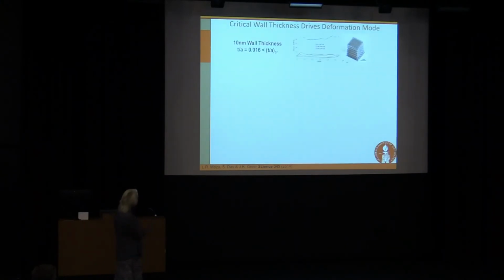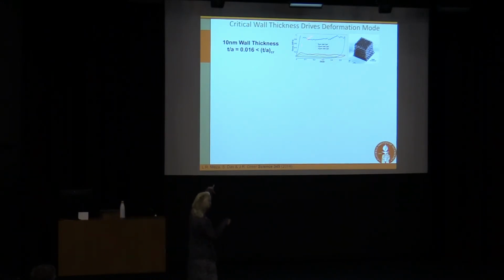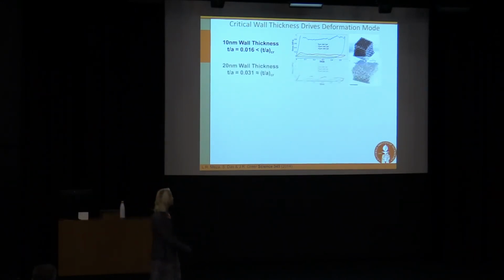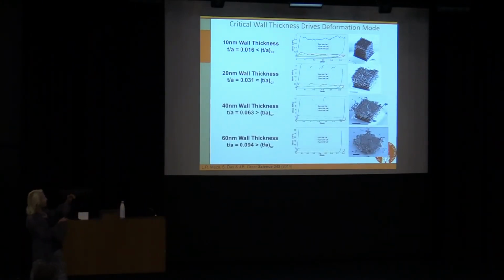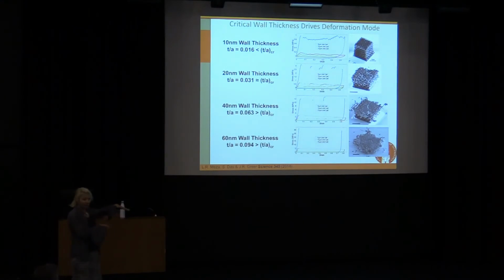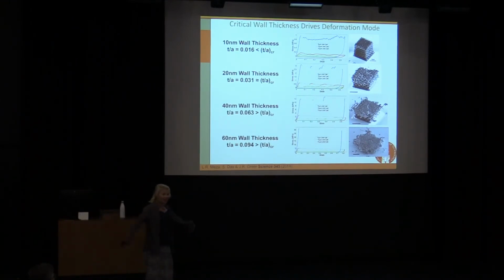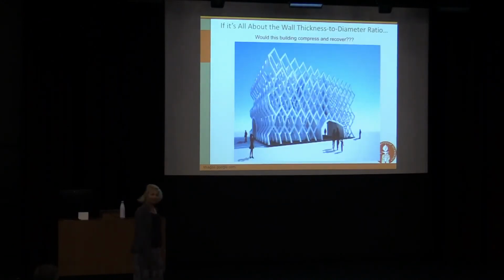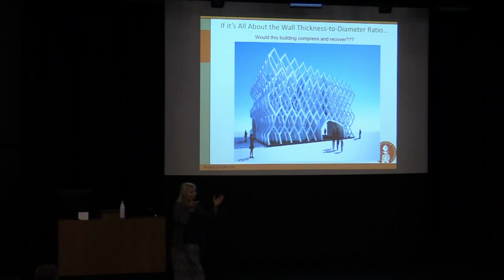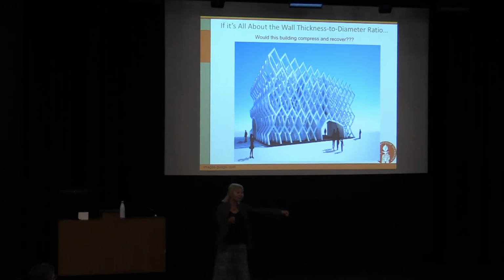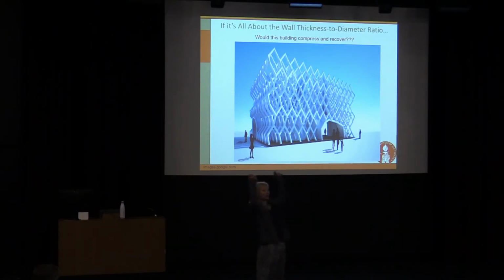Okay, all right, so we see that maybe that's what explains the recoverability. Well, sure enough, let's look at that. So for the 10 nanometer wall thickness, that ratio is below the critical ratio. And so we can see that for various unit cells, your structure always recovers, so that seems to be consistent. And as we increase the wall thickness and we get to the critical ratio and then deviate further and further from it, our deformation becomes much more stochastic, much more jerky, and then just, obviously, this guy doesn't know what to try to recover. So the answer lies in mechanics, right? So what that tells us is that if we were to build a building out of big tubes whose wall thickness is 10 centimeters and whose diameter or radius is 3 meters, and we preserve the T over A ratio, and we build a building like this, some giant comes and steps on it, it'll just spring right back after, right?